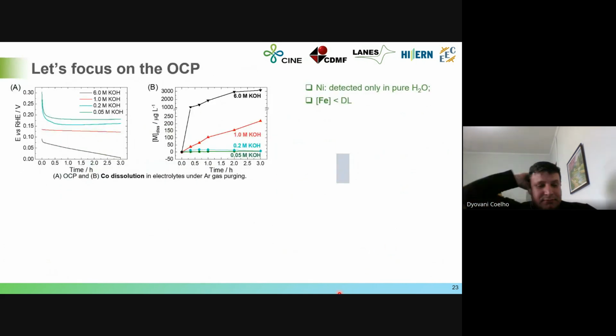So let's concentrate on what is happening with the catalyst just at the open circuit potential, because here we have a huge dissolution of cobalt in the catalyst. And here you can see that the cobalt dissolution is directly proportional to the alkaline concentration of KOH in the electrolyte. So the higher the KOH concentration, the higher the cobalt dissolution, which means that working with this kind of catalyst containing a lot of cobalt in conventional electrolyzers or alkaline electrolyzers is not a good idea, because they use 6 molar KOH, and in 6 molar KOH, as you can see here, the catalyst dissolution is really higher compared with the other ones.